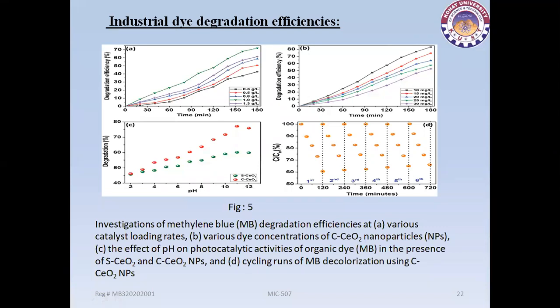Results show that the dye degradation efficiency increased with increasing pH, as shown in Figure 5c. As methylene blue is cationic, it would be easier for the positively charged dye to adsorb onto the negatively charged surface of the catalyst, as determined by zeta potential, Figure S2, and a basic solution with high pH promotes the catalytic reaction.